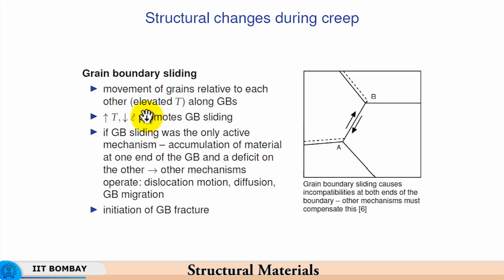So, high temperatures and low strain rate promotes grain boundary sliding, and that is because at high temperatures you have greater diffusion taking place, and therefore, grain boundary sliding also takes place. At high temperatures grain boundaries are also much weaker. They have much less strength, and therefore, the strain at the grain boundary becomes higher, shearing becomes easier at the grain boundaries. So, that is why it promotes higher grain boundary sliding.